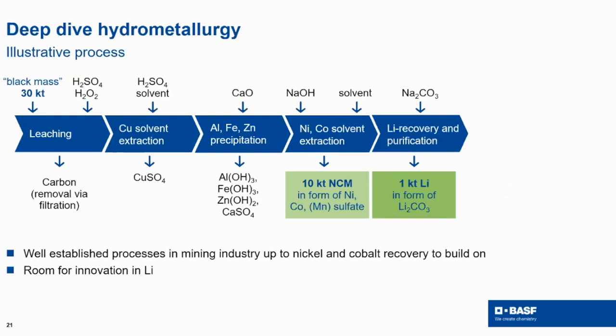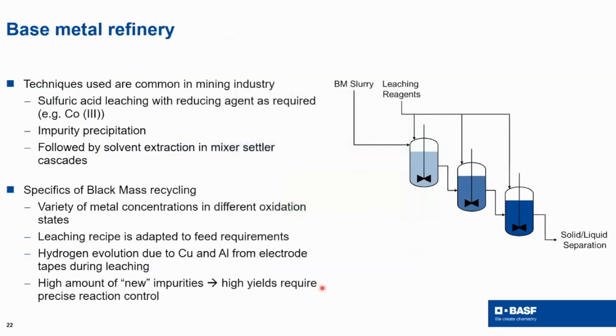And at that stage, I can only reiterate what I said before. Here, under the nickel, there's a lot of technology to build on. However, it needs to be adjusted. Room for innovation is the lithium part. Let me talk a little bit about the adjustments in that base metal refinery. As I said, it's typical there to leach the black mass with sulfuric acid and afterwards go for an impurity precipitation followed by a solvent extraction in a Mixer-Settler cascade.